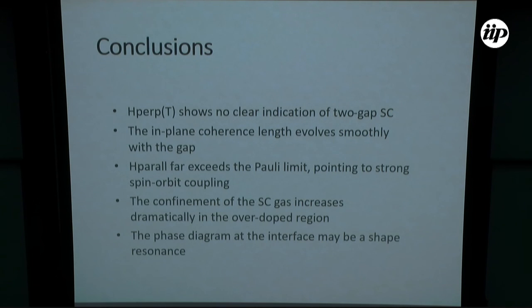HC in parallel field exceeds the paramagnetic limit, as has been observed also in a thin film of niobium-doped SrTiO3. And now, taking into account the confinement, the deconfinement effect of the gas across the phase diagram and the carrier density that we modulate with the field effect, we can explain the phase diagram we observe as probably mainly due to a shape resonance of the system. And with that, I thank you for your attention.